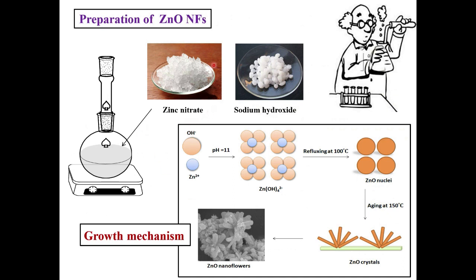This is the preparation method for the zinc oxide nanoflowers. For that we have used zinc nitrate plus sodium hydroxide. We have changed the concentration of zinc nitrate as well as sodium hydroxide, and according to the change in concentration we have maintained the pH of the solution at 11. When zinc nitrate and sodium hydroxide react, they form zinc hydroxide, and further the zinc hydroxide is refluxed at 100 degrees centigrade to form zinc oxide nuclei. These nuclei are put for aging at 150 degrees centigrade, and the nano zinc oxide nuclei are converted into zinc oxide crystals, and then into the nanoflowers. This is the complete mechanism.